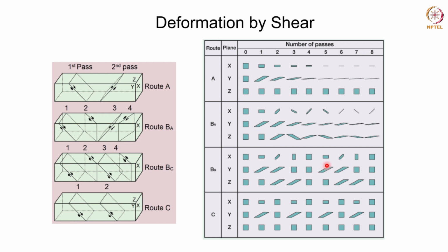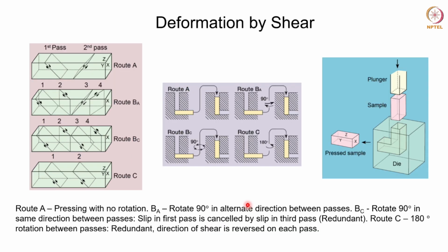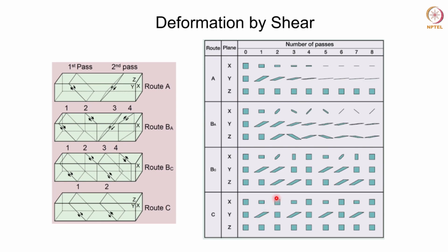And in case of route C, it is 180 degree rotation. So in every second pass, the element will be restored. That's what I said before also. It's a redundant process. The deformation is redundant because the direction of shear is reversed in each pass, and every second pass any element inside the material is restored, because here the rotation is by 180 degrees in the same direction.